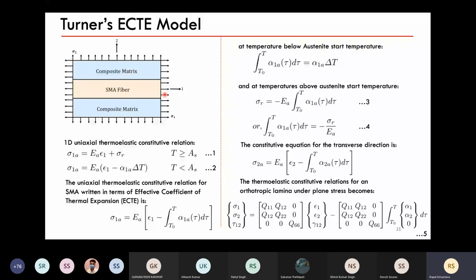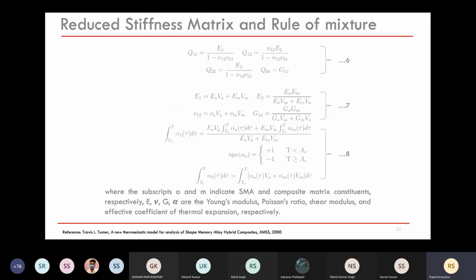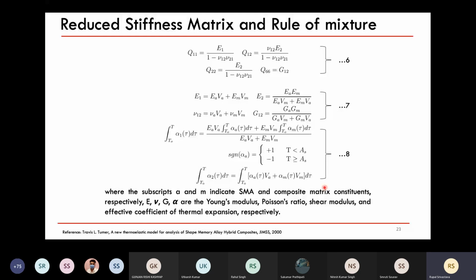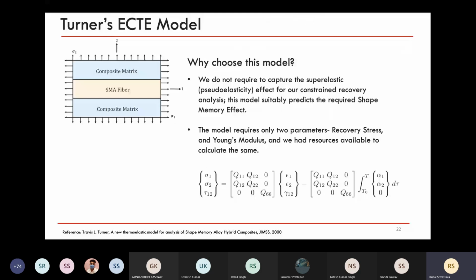So when the material properties are all different in all directions, along one it is different, along two it's different, and also along the z direction, that is the thickness, it is different. The equation is somewhat like this. And this part is added because we have SMA embedded. If this part wasn't there, it would have been a normal orthotropic material with no temperature involved. Okay, so what are these Q matrices? These are reduced stiffness matrices, and they are calculated by Halpin-Tsai equations and by rule of mixtures. And the elements, Q11, Q12 and all, as we saw previously, are nothing but your Young's modulus in one direction, your nu12, nu21, and Young's modulus in two direction.